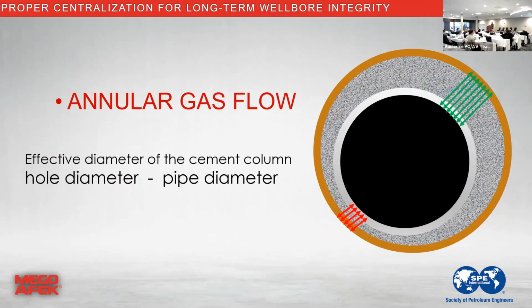Intuitively, also, the annular gas flow is going to cause a larger impact on the thinner side as well. Now, I don't remember exactly the equation, Daniel, but you take into account the difference between both diameters of the pipe and your hole. So if your hole is 17 and a half and your pipe is 13 3/8, you use that difference in diameter, you call it effective diameter, to calculate your flow potential. That'll give you a number, assuming static gel strengths and other stuff, the length of the column. But my point is, mathematically, 17 and a half minus 13 3/8 is what you use to calculate your flow potential.